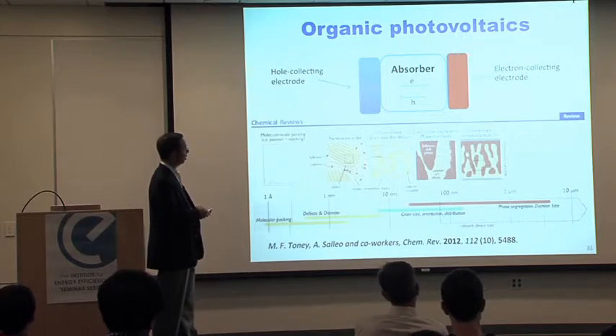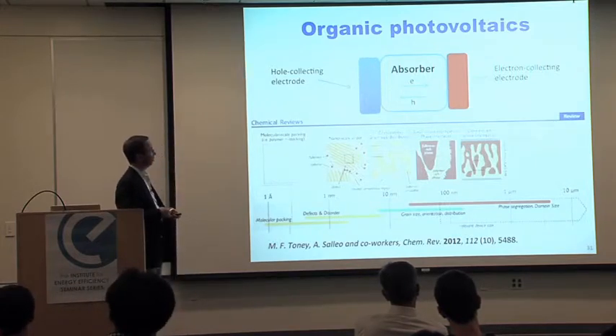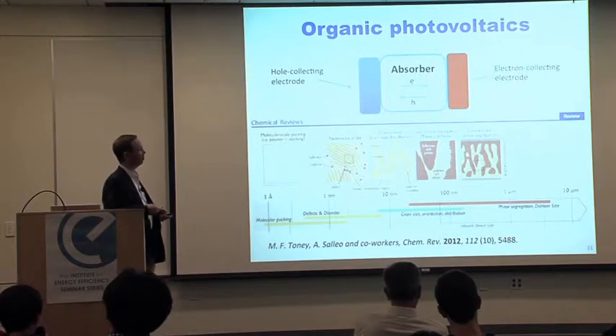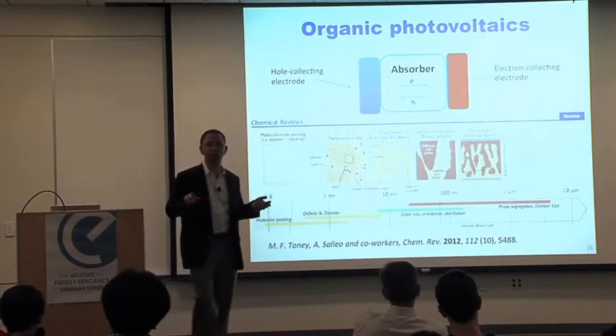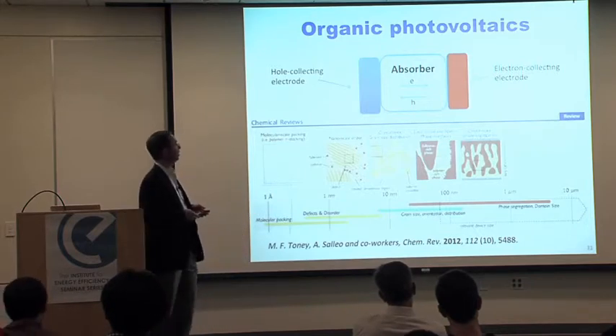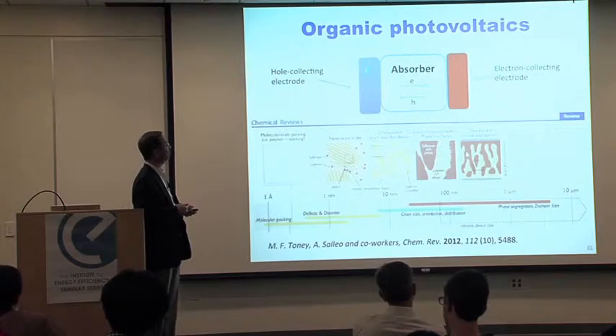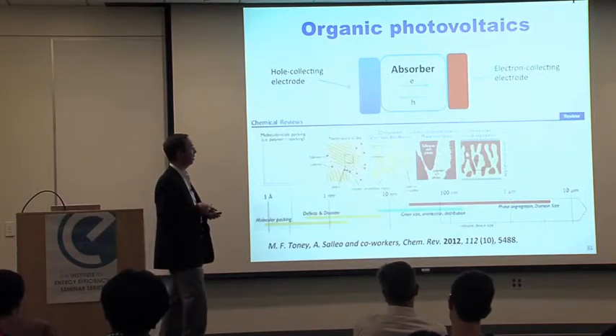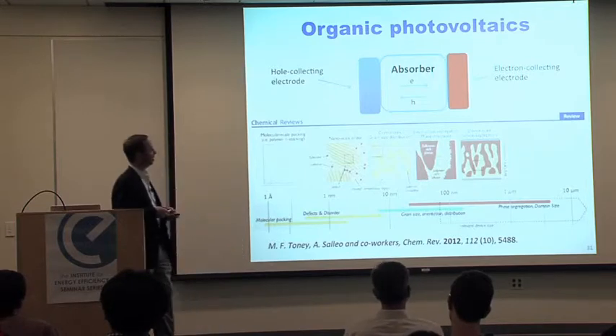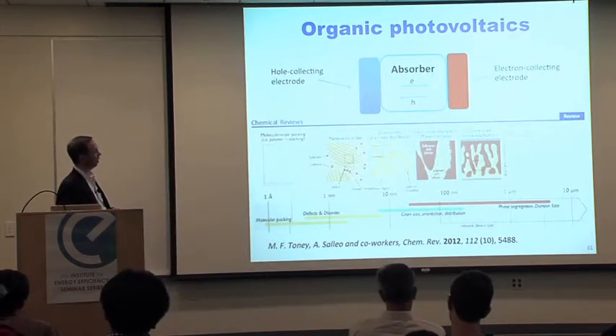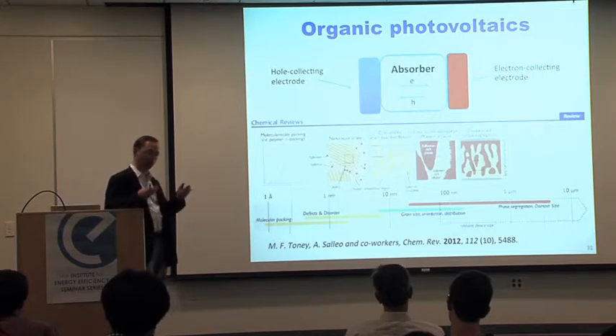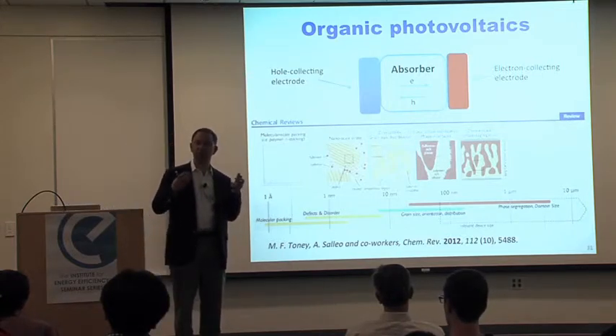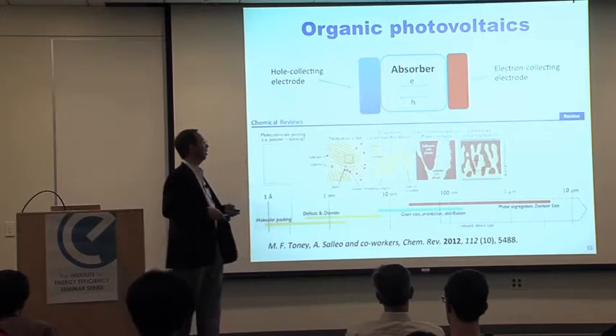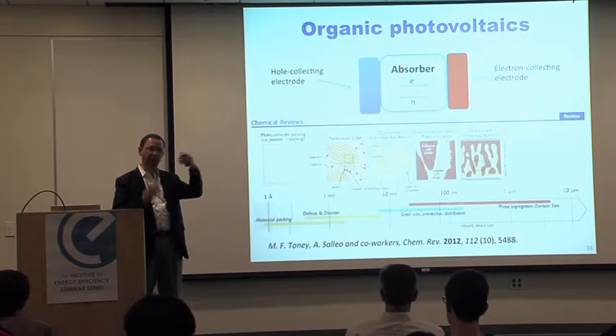I'm going to use the red color to describe an electron collecting electrode, a blue color for a hole collecting electrode. And so the analogy, if you're familiar with a conventional PN junction type or crystalline silicon cell, you have your asymmetric device where on one side you have a p-doped layer, on the other side the n-doped layer, and in the middle you have that membrane that separates holes in one direction and electrons in the other direction. Here, that asymmetry in organic solar cells is caused by the fact that you're mixing donor and acceptor-like compounds which have different electron affinities and different ionization energies, and you make the transfer of charges asymmetric.